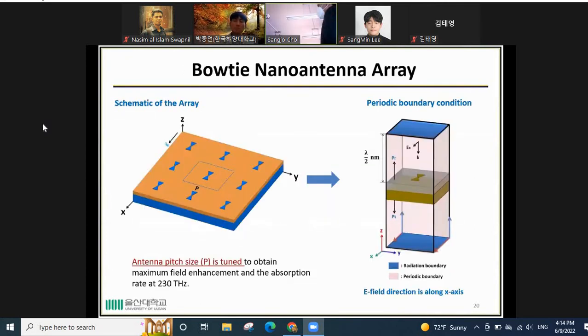And after getting the optimum parameters from the single antenna, we move to the nano antenna array, and this is the schematic of the antenna array. In the antenna array, we use a pitch size, which means the distance between antenna centers. We also tune this pitch size to obtain the maximum field enhancement and also absorption rate at 230 terahertz. And this is the simulation method. We are using a periodic boundary condition, where the electric field direction is along the antenna axis.